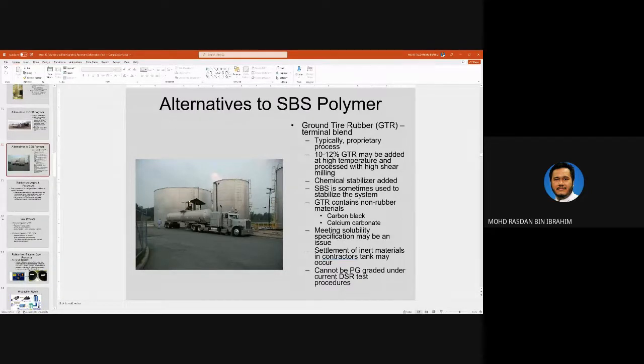So you can add chemical stabilizer to stabilize the system, or you can mix it with SBS. This tire rubber contains other materials such as carbon black and calcium carbonate. So meeting the solubility specification may be an issue. When I first got into the blending of rubber into bitumen, this was one of the problems.